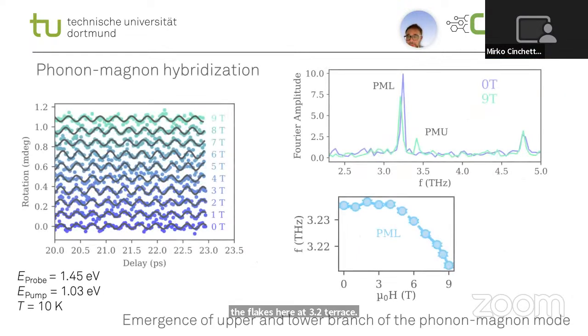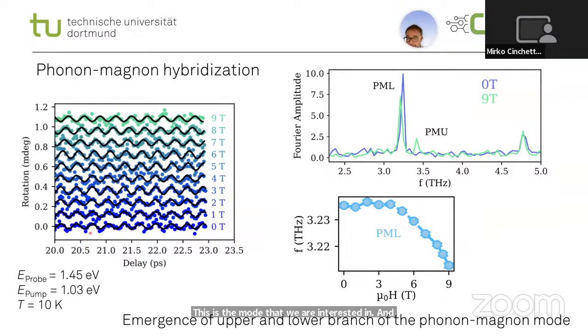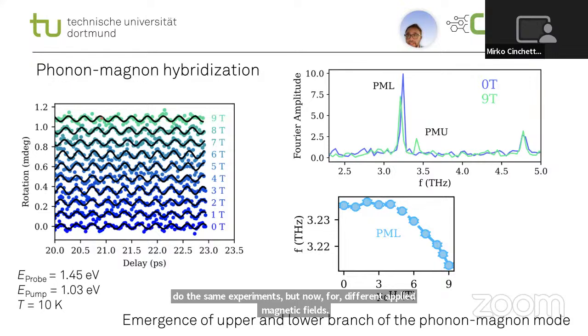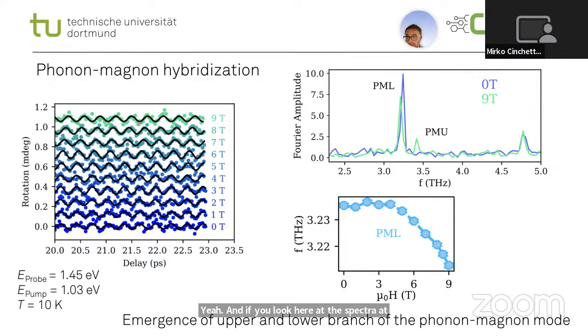Now we do the same experiments, but for different applied magnetic fields. If you look at the curves that we recorded at 9 Tesla, and do a Fourier transformation, we see that we don't have only a single peak at 3.2 terahertz, but this peak is split in two. These would be the two branches of this phonon-magnon polariton that we are generating in the presence of the magnetic field.